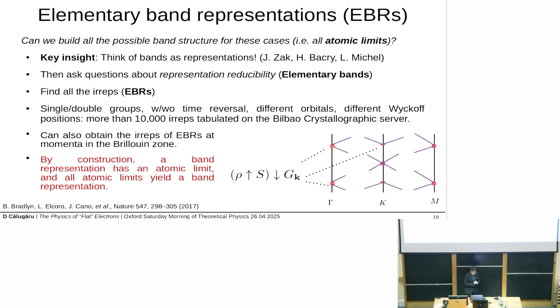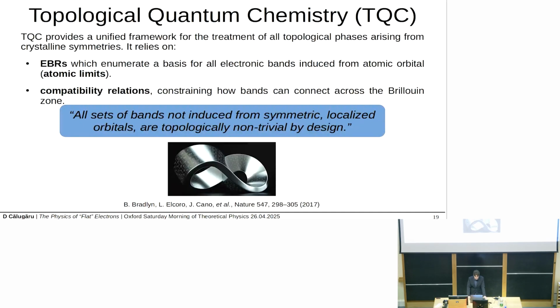To cut a long story short, what people have done, and only recently in 2017, is take all the possible space groups and all the possible ways of arranging orbitals in them, and carefully tabulate every single band that can arise in such a system, every single band that can arise from localized real space orbitals. And then they said, well, we know all the bands that have a localized real space description. We also know all the possible bands, because we know how bands should connect in momentum space. And they reached the following conclusion: all sets of bands that are not induced from symmetric and localized orbitals are topologically non-trivial by design.